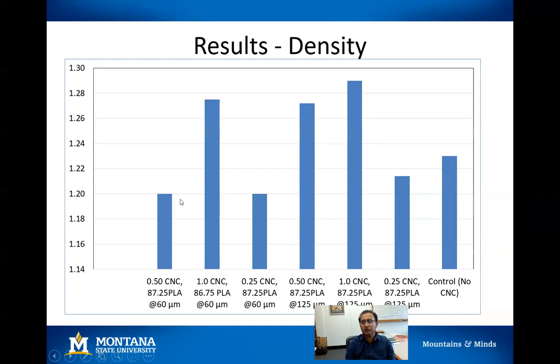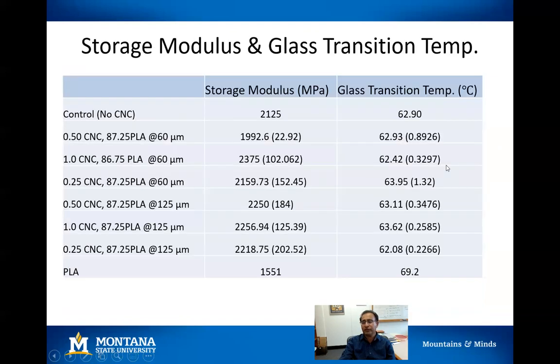So now I'm going to get into results. The first thing we noticed among all these formulations, this is your control where there is no CNC, is that as we added CNC, the density of the samples went up. So the 1% samples and another 1% sample showed a density around 1.29, whereas for the control, the density was 1.23. The second property we looked at was the storage modulus and the glass transition temperature of composites.